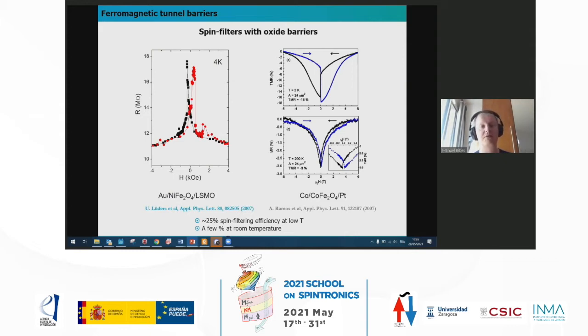We had probably some defects in our devices, so we could see some TMR at low temperature, but not at room temperature. But then a few years later, actually the same year, there was a group also in Paris-Saclay at the CEA who grew this film by MBE. They could observe a small TMR at room temperature. So this works. The effects are not very spectacular, but this works. Probably the quality of the material is not sufficient to produce these very, very large effects.